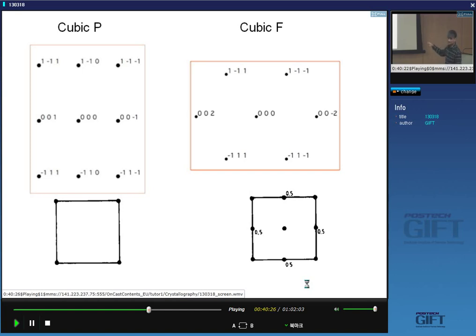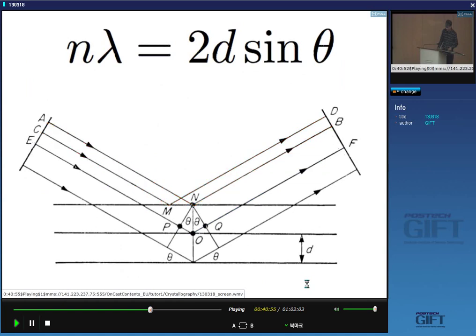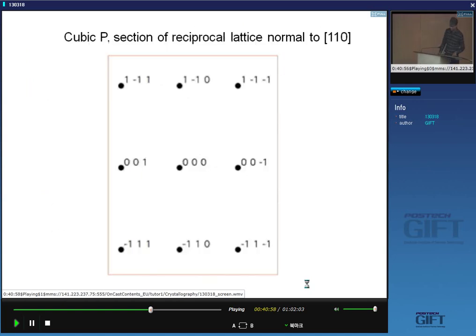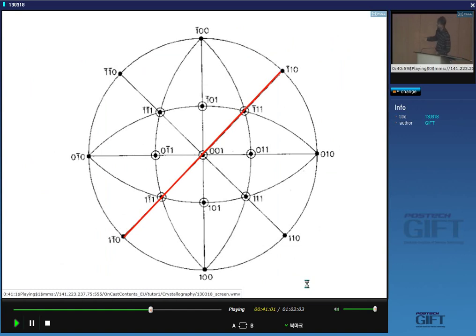Okay. So now the shape of the pattern looks different because of the specific reflections which are missing. So here you have a distorted hexagon, whereas this is a rectangle, even though both of them represent 110 zones. If I go back to my stereogram, there's your 111, which we saw on the pattern, and the 110 and 001, which in the case of cubic F would be 002 and 220.